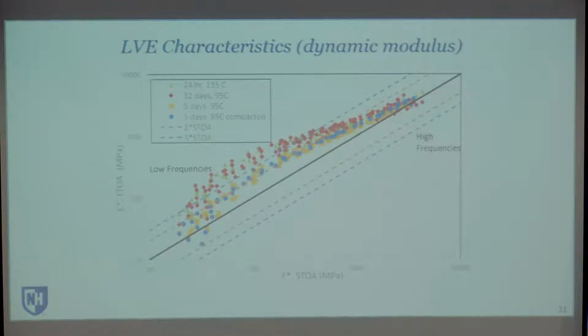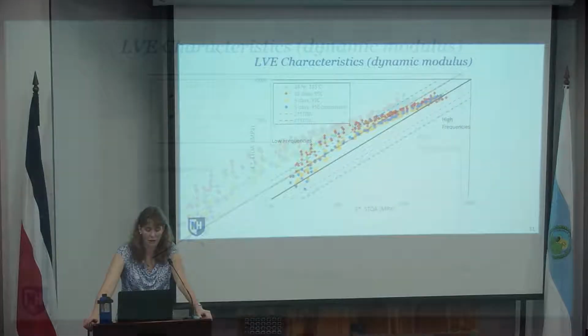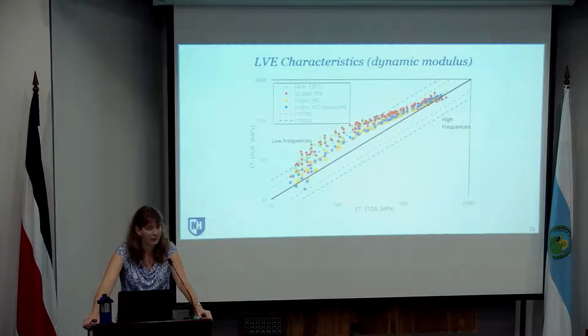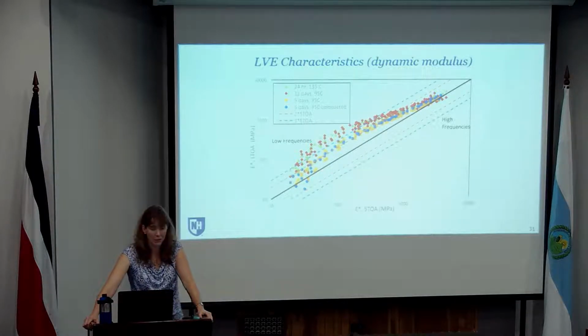Okay, you can also look at the impact of the aging as a function of how it changes, or the different long-term aging protocols as how they change from the short-term aging condition. So what this figure is showing is the dynamic modulus, or the stiffness, from the short-term aging condition on the horizontal axis, and the stiffness at each long-term aging condition on the vertical axis.